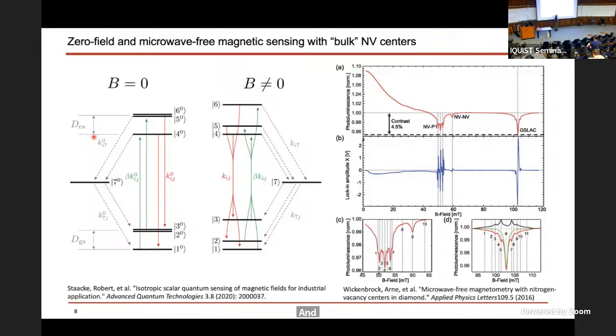On the right here is a spectrum that shows the change in this photoluminescence as a function of magnetic field. The exact level where all of these transitions cross is at about 100 millitesla. This feature here is due to contributions, if you're looking at ensemble NV magnetometry, from other spins that are not along the direction of the magnetic field application. Even though you're looking at several percent changes in the photoluminescence, this provides a pretty nice, easy way to measure magnetic field.